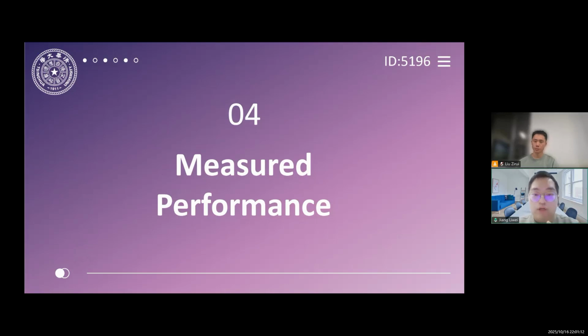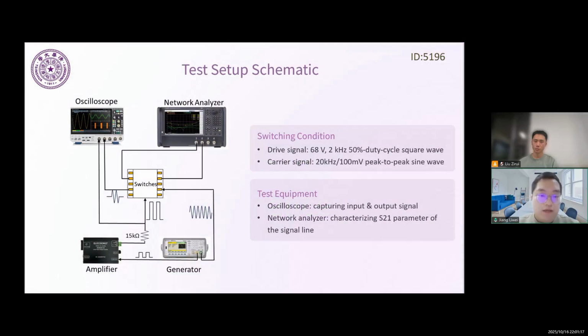For electrical testing, we built a custom setup. It contains a network analyzer to measure S parameters, an oscilloscope to capture time-domain waveforms, and a signal generator and amplifier to drive the switch. We apply a 68 volt, 2 kHz square wave to the gate. This is the actuation signal. And we feed a 100 millivolt, 20 kHz sine wave into the RF port as a carrier signal. We also use a through line reference on the same chip to de-embed the loss from the CPW and the probes. So we are measuring only the switch performance.